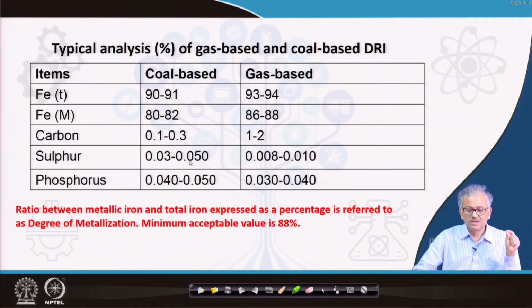In the coal based process it is a little higher, because the DRI is in direct contact with the coal. And you can see in the gas based process the sulfur is much less, 0.008 to 0.01. So, it is much less compared to the coal based process, because in the coal based process the DRI is in direct contact with the coal, which is a source of sulfur. And the phosphorus is more or less similar.